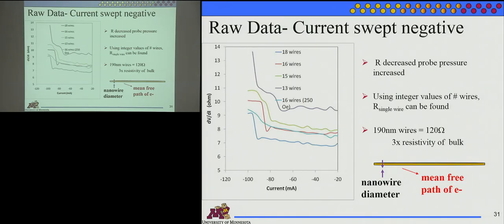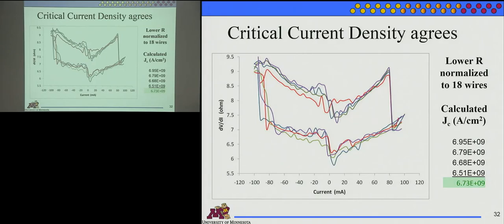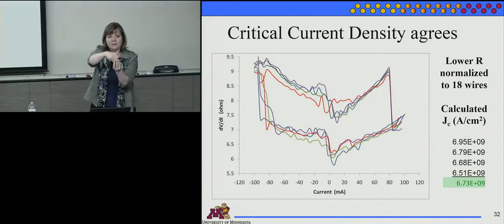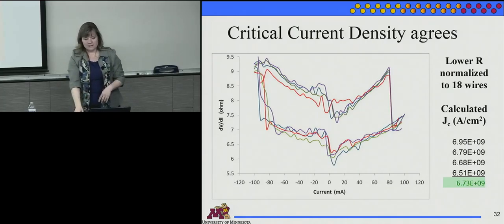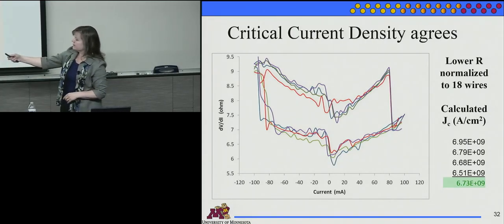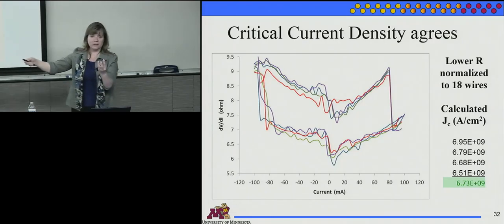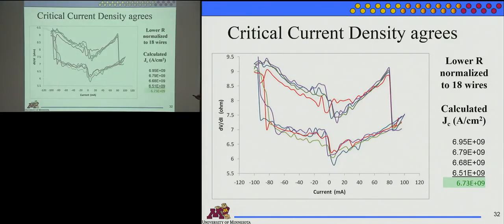So Nanoletters said, well, actually, wait, let me first say, we had all our nanowires. We're coming down with a probe. We pick up more, and we end up seeing different resistances. So we said, why don't we, when we get to this spot, adjust the pressure till we get the same, somewhere around 9? There's some noise, but you have the same number of nanowires at about 9 in all the different samples. So these curves were adjusted by normalizing them to the value of 18, but every single one of these curves was measured exactly as you see it here.